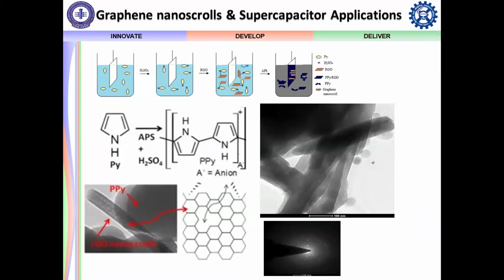Yes, work we did around 2 to 3 years back, where we used graphene as one of the materials, and during the development, we were also trying to enhance the energy storage capacity of the micro supercapacitor. For that, we used graphene, along with polypyrrole as a binding material. By utilizing two reactions at the same time, we used ammonium persulfate and H2SO4 simultaneously. We developed the method for the generation of graphene nanoscrolls.